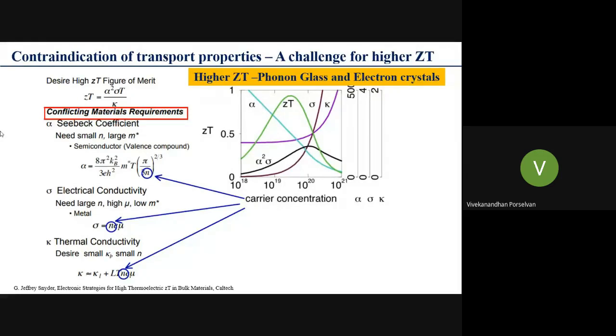We should have the very, very lower thermal conductivity. Why is it happening? To achieve a higher Seebeck coefficient, we need a small carrier concentration, that is n, and a higher m*, the effective carrier mass. If you're talking about the electrical conductivity, we need a larger carrier concentration, higher mobility, and lower m*. And talking about the thermal conductivity, the desirables are